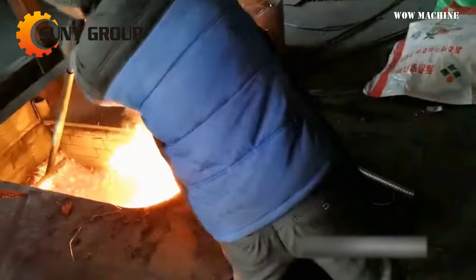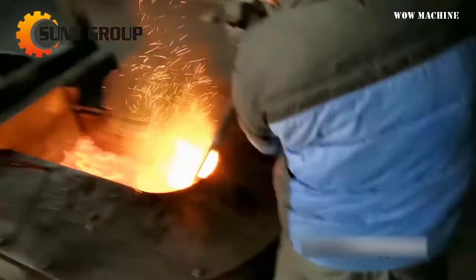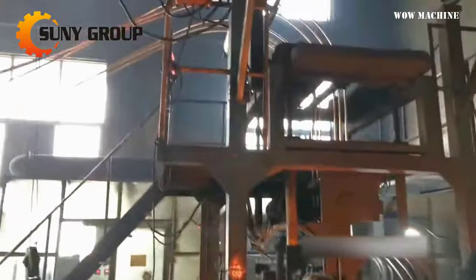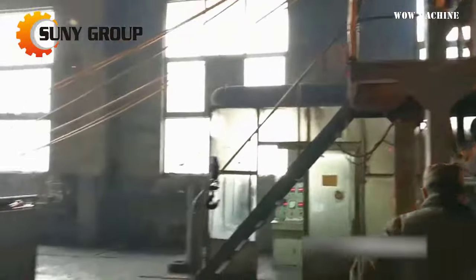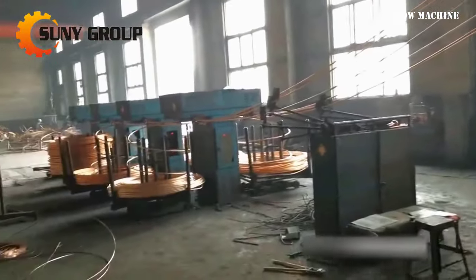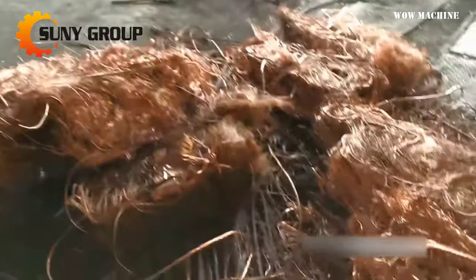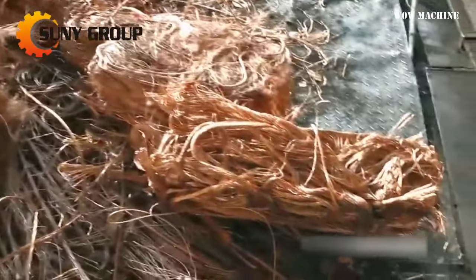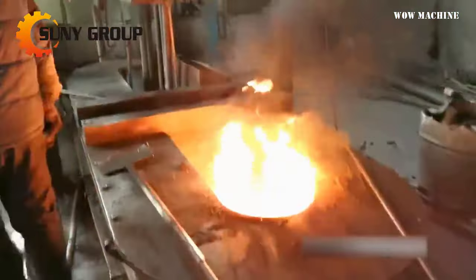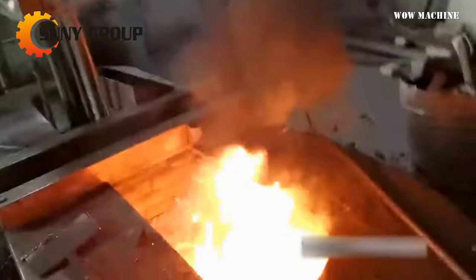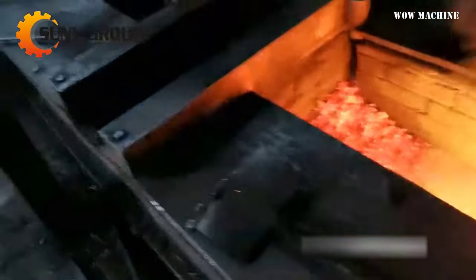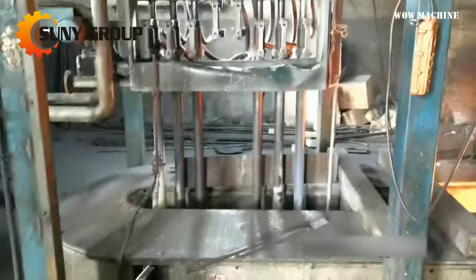This furnace, often a shaft or rotary type, is heated to around 1085 degrees Celsius, 1985 degrees Fahrenheit, the melting point of copper. During this phase, impurities separate from the molten copper. To further purify the molten copper, fluxes, chemicals that help bind impurities, are introduced. These fluxes form a slag with the impurities, which can then be removed, leaving behind high-purity molten copper.